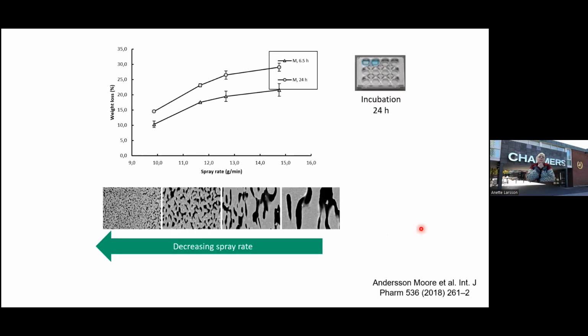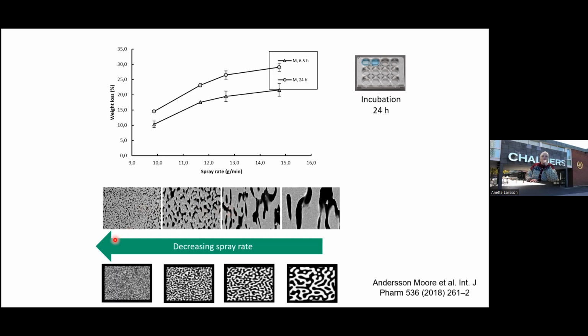Another way that is a little bit less discussed is that one can also create different pore structures through the processing and the creation of the coating. So in this case here, we sprayed very slowly, which means that they dried faster, and that they had dried faster meant that they were arrested earlier in this development of the phase separation. So that gave a direct influence on the pore structure, but also on the permeability. So a decrease in the spray rate locked them earlier.